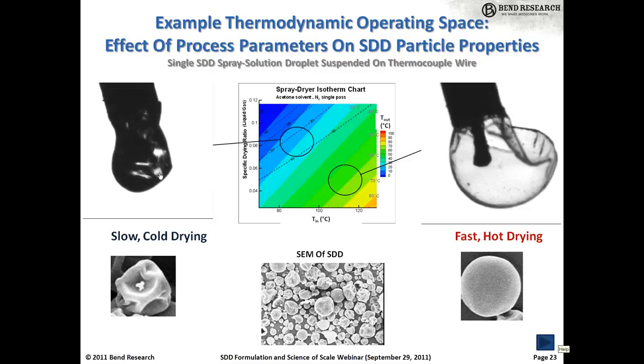The converse is true for the cold outlet drying conditions, where the solvent is able to diffuse through the polymer skin at an adequate rate, and you end up with these raisin-like high-density particles that have a little bit less compressibility. Of course, for any drying condition, what you really get is a distribution of particle types, but the process is very amenable to tuning so that you end up with more of one type of particle based on the thermodynamic conditions. And of course, these types of morphologies obviously affect downstream tablet manufacturing, and we'll talk about that a bit more later on.